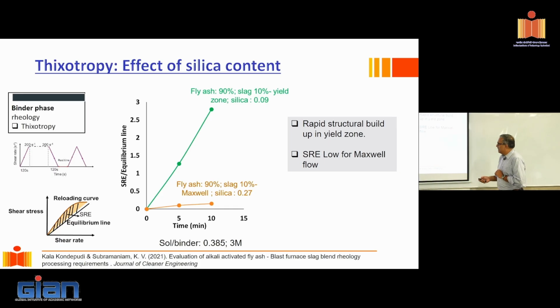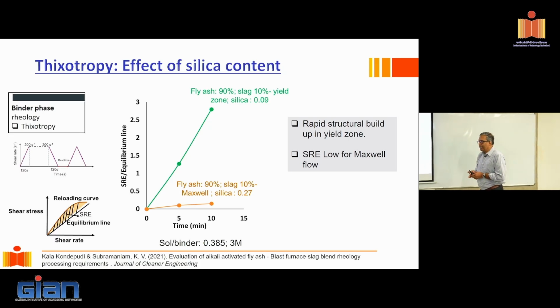What we are measuring here is a 0 point is after I smash the structure. So after I've done this, I wait for some time and then I do a ramp up, ramp down. So I get a curve like this and I measure the area in between this, which gives me the energy that is required to break the structure after it restructurates. What do I mean by that? Well, we go through this. I ramp it up to a certain rate, hold the rate constant, completely smash the structure, ramp it down, then hold it constant for some time, and then do a ramp up, ramp down.